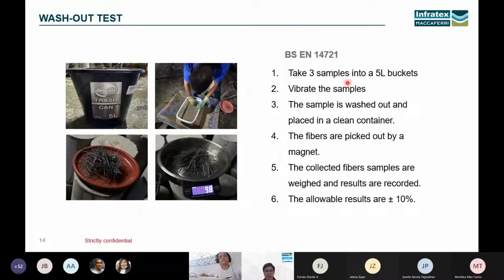Then we separate the steel fibers from the concrete mix by vibration, washing out the mixture, then picking out the steel fiber with a magnet, then washing it again. Then we weigh it. The allowable result must be within plus or minus 10% to allow the mixture for pouring.